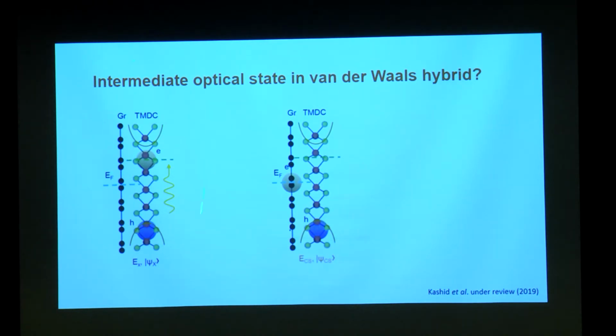This is the optically excited van der Waals heterostructure. There's an exciton that has formed within the transition metal dichalcogenide layer. The graphene layer is neutral. And then to get the electric current, I have got the hole remaining here, and the electron is at the Fermi energy of the graphene layer. What I'm saying, there's an intermediate state.